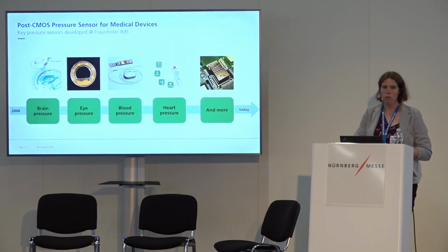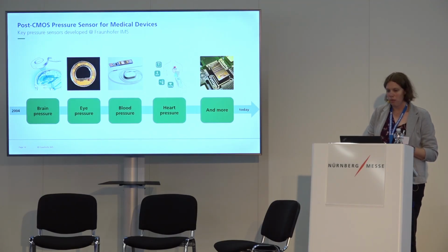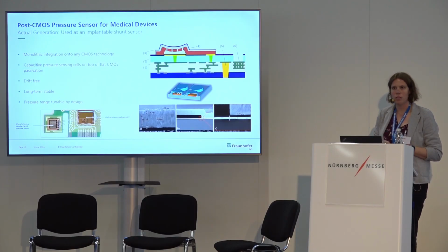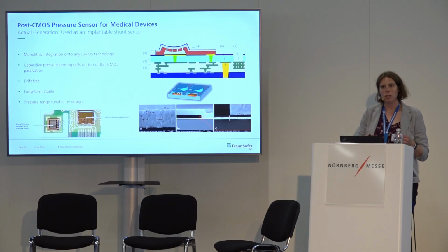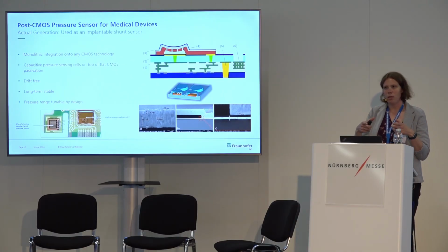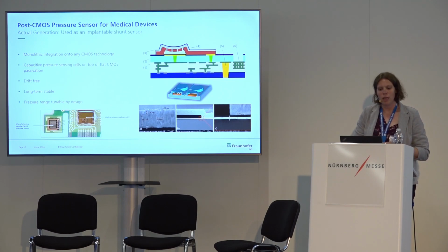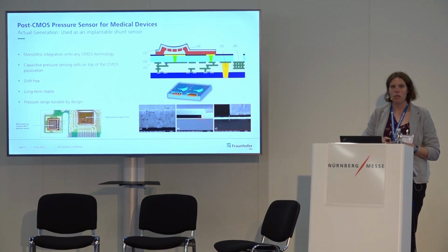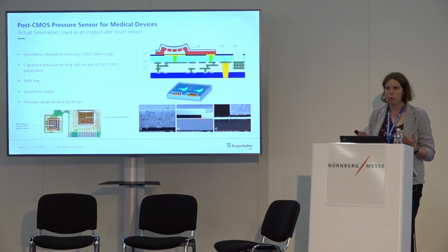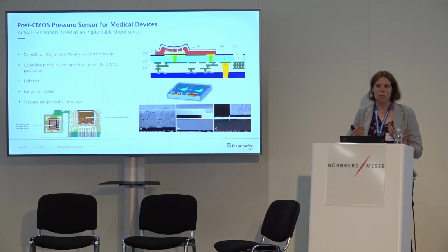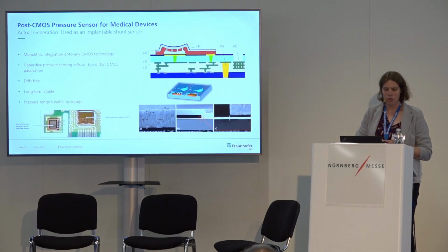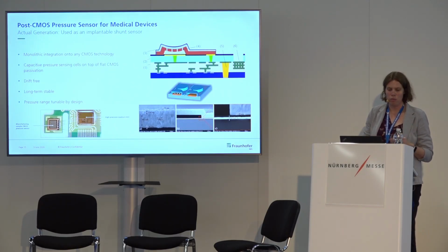Here we are improving more and more our pressure sensor process, so we can have a deeper look inside it. This process is also a monolithic integration onto a CMOS technology. Here we really start on a CMOS wafer, and then we are producing our process on top of this wafer. So no bonding, but really processing on top of this CMOS wafer. You can see it's a capacitive sensor. You can see the membrane on top of it. There also an ALD layer was used. And these sensor systems are drift-free and really long-term stable, which is a good advantage or a need for implantable pressure sensors, because you do not want to change the sensor after a few months. It needs to be inside the brain for several years.